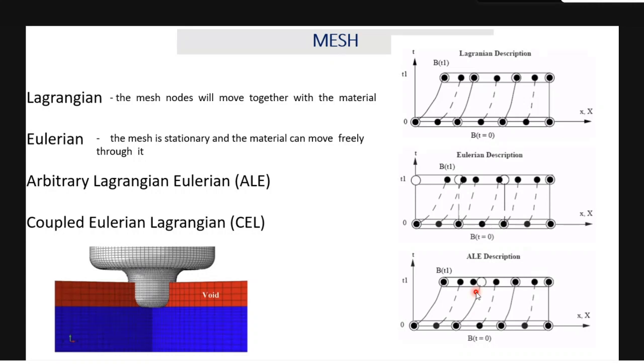Previously, flash was considered an unwanted material in friction stir welding, and recently it is one of the indicators to know the material flow and to know the defect formations in friction stir welding. If you have an excess flash, without destructing the sample you can say that you will have a defect inside. So it is very important to model the flash also. The coupled Eulerian Lagrangian supports that, because in this framework it can accommodate a lot of strain of the material there.